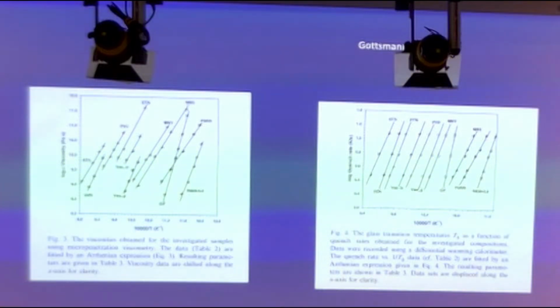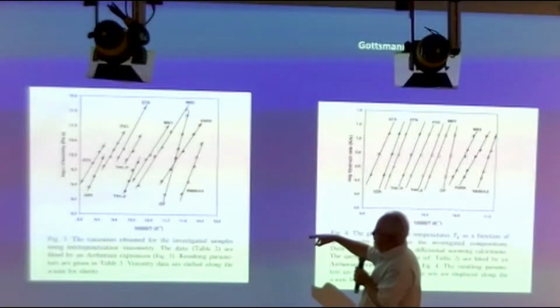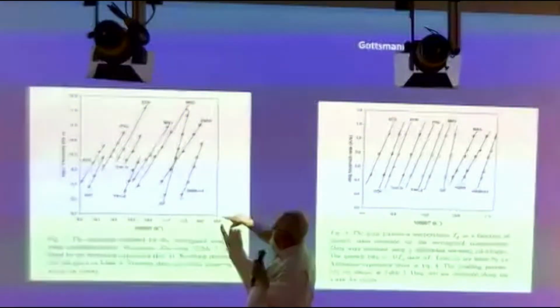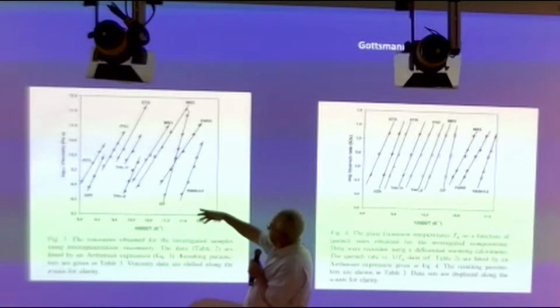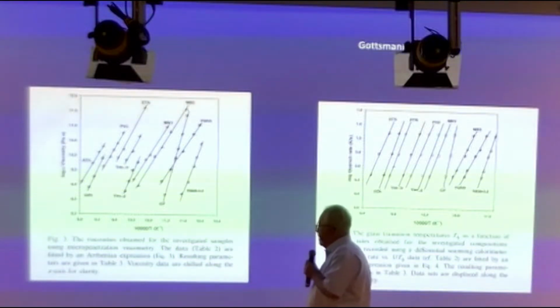It's what makes a liquid able to flow rather than simply be compressed and elastic. It's the ability of the atoms to actually move out of the way during these deformation events. And so, what we have here is a plot of the logarithm of the viscosity as a function of temperature for various compositions here, as you can see.